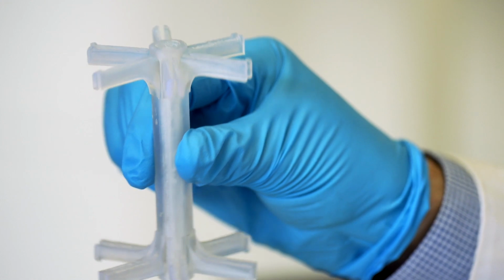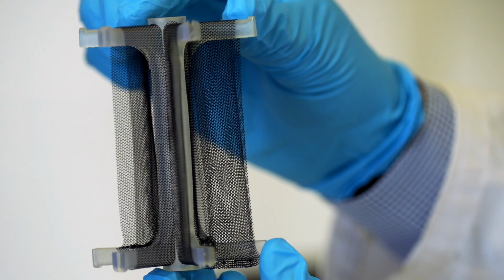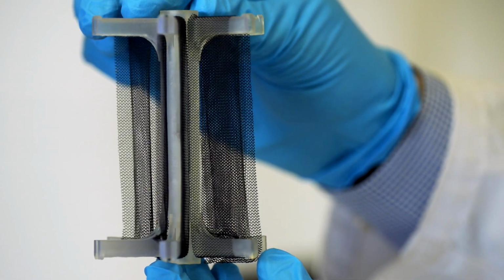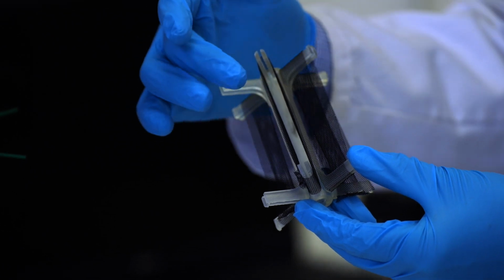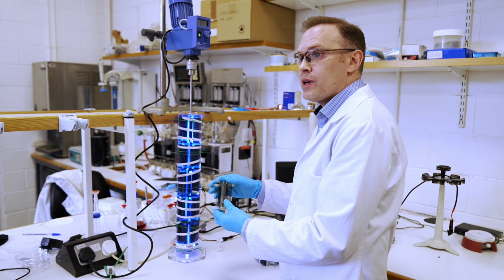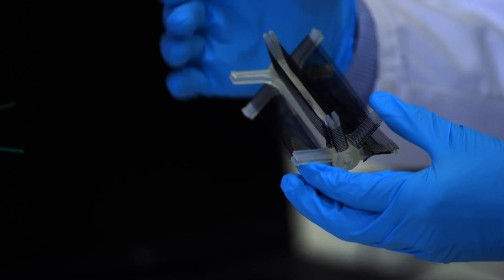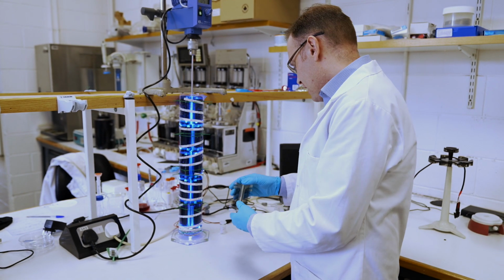The shape of them, we came up with this shape here so that we could fix the netting substrate, or the netting pieces. This is what we came up with. These are small nylon netting pieces, and onto these nylon netting pieces we immobilised the titanium dioxide, or the photocatalyst. And to look at it with the naked eye, you don't see it, but it is there.